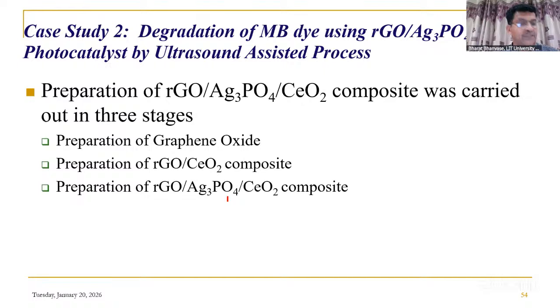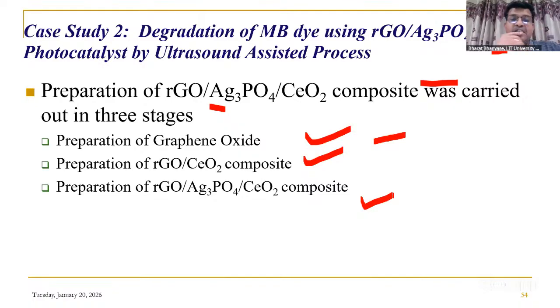Here in the preparation of reduced graphene oxide, we have loaded Ag3PO4 and cerium oxide. This composite was prepared and used as a photocatalyst for the degradation of MB dye. So the first step is preparation of graphene oxide, second step is preparation of rGO/CeO2, third is rGO/Ag3PO4/CeO2 composite.